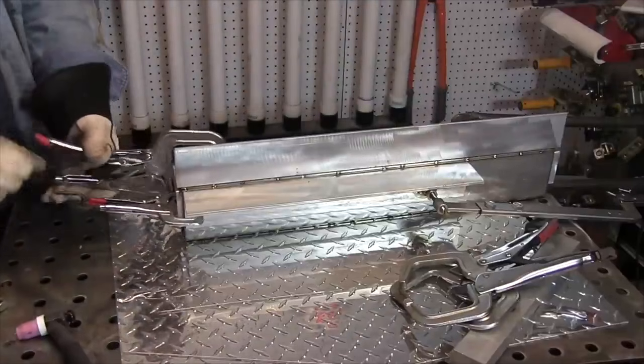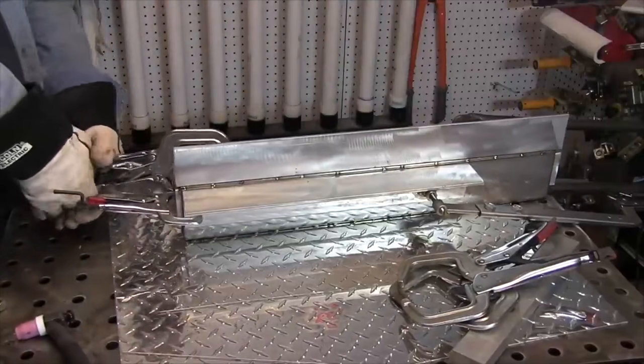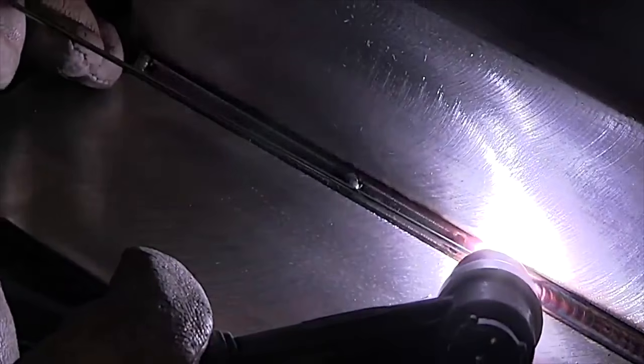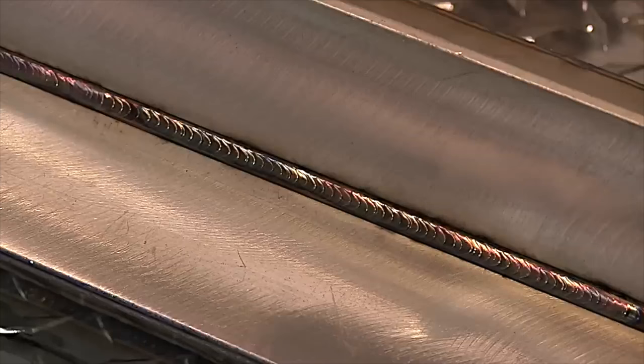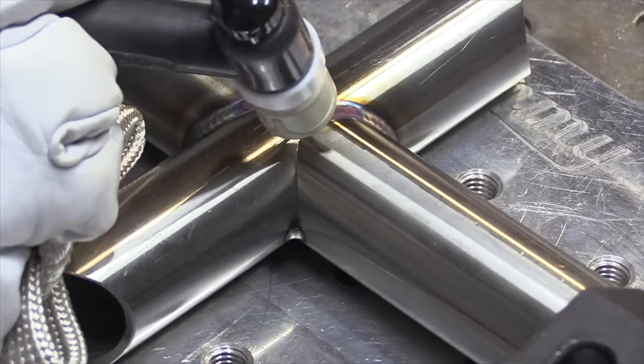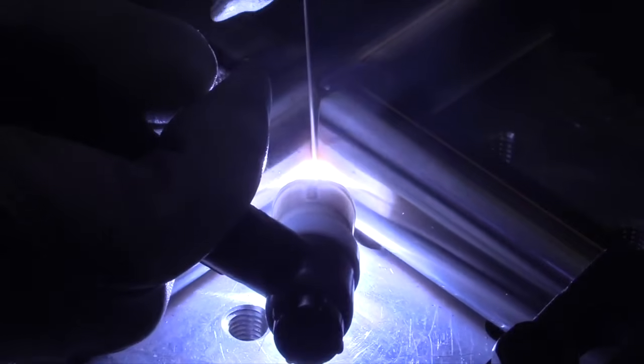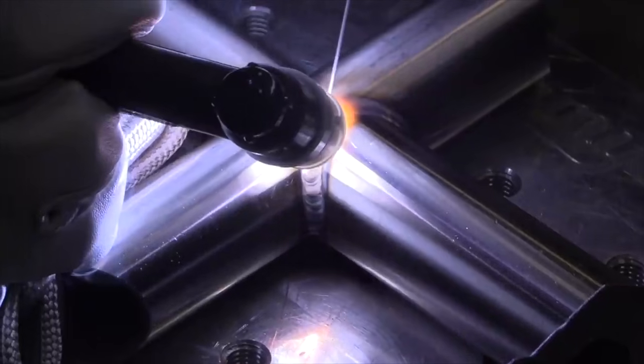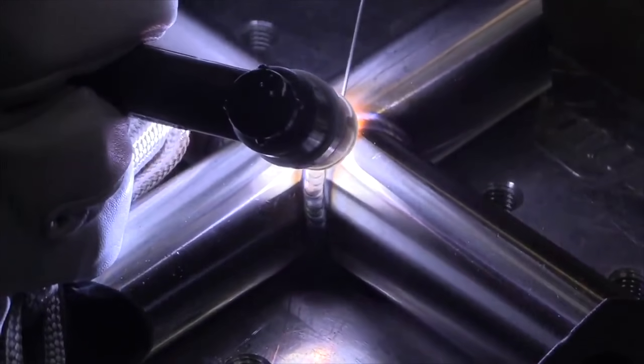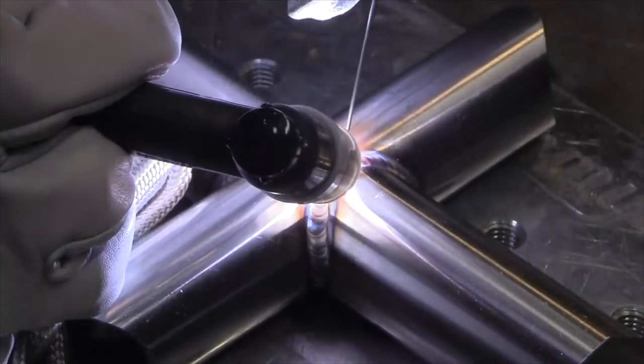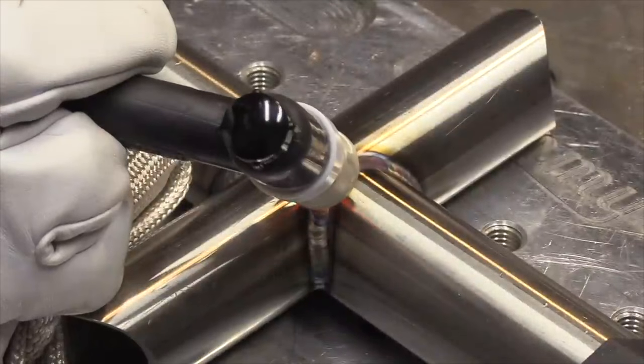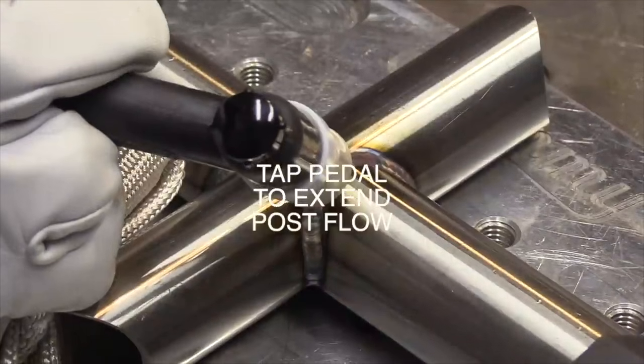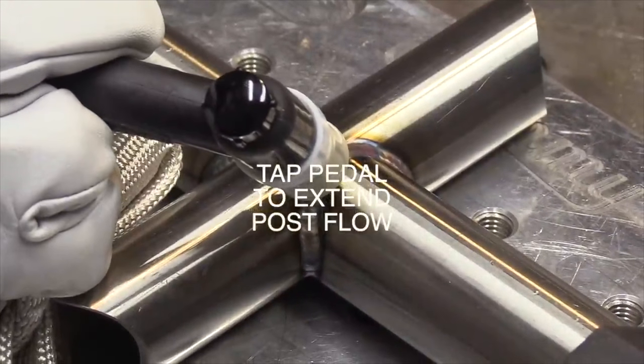In order to maintain the corrosion-resistant properties of stainless, heat input is a big consideration. I don't mean less amperage. I mean heat input can be lessened by increasing the travel speed and also using chill bars. And a 3-second rule is a really good idea for a job like this on tubing. In other words, if you can't get a puddle and get it going within 3 seconds, you probably need a little bit more amperage. You got to get going quick to outrun the heat. It's time at temperature with stainless steel. If you get it too hot and hold it there for too long, you start to lose the corrosion resistance properties.